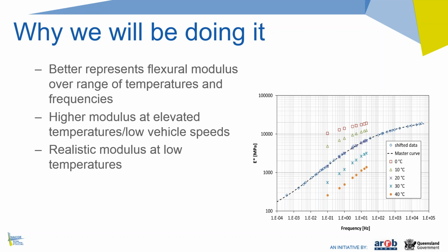Well, this will also result in a higher modulus at elevated temperatures, and that's mainly because our current Austroads method underpredicts the modulus at high temperatures and low frequencies, which is obviously very important for a warm climate like in Queensland. And we also get more realistic values at low temperatures, as I will be showing on the next slide.